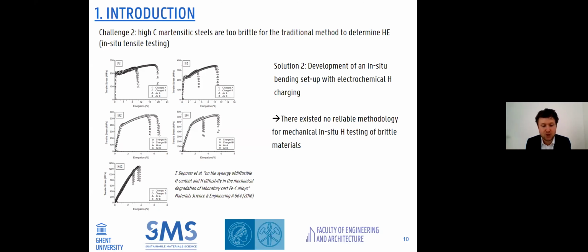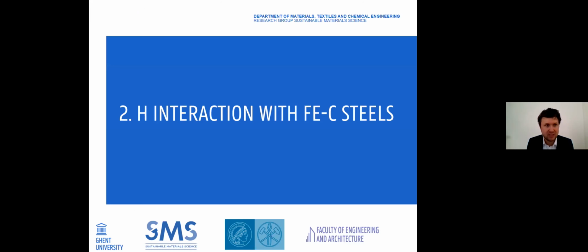M4, containing 0.4% of carbon, was also tested, but this was impossible as the samples already broke upon clamping or very fast during the tensile test. So there is no way to evaluate embrittlement for very, very brittle materials, which are martensitic. So that's why we developed an in situ bending setup with electrochemical charging. Again, in situ, because we don't want to lose hydrogen in between charging and testing. So this is the introduction.